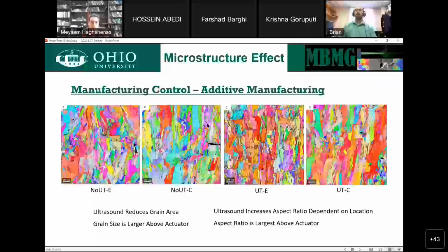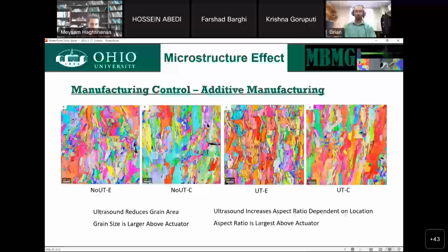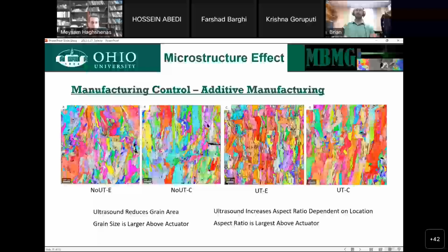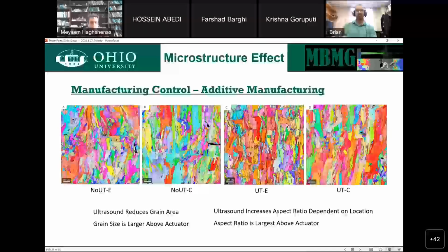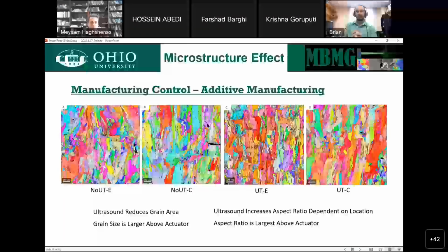If you want the control, which is where we ultimately want to get to with this, where you can change frequency and intensity, because cavitation threshold is dependent on those two things. The higher the frequency, the lower the intensity you need to get the same result, though there's a couple of studies that show the end result is still slightly different. If you want to be able to change this for true tailorability, you're probably looking in the order of tens of thousands. But compared to the cost of the full machine, it's nothing. Exactly. It's very much affordable, I guess.